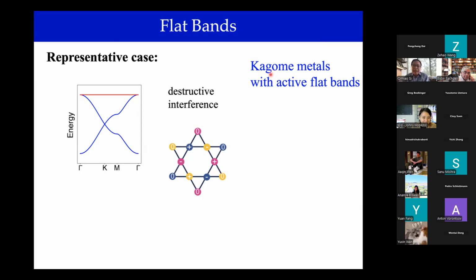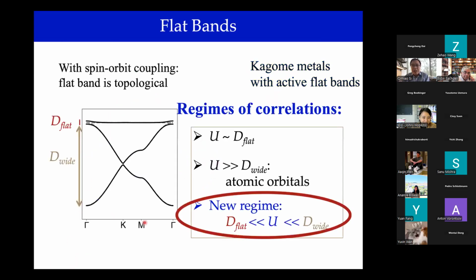is something like Kagome metal. If the chemical potential is sufficiently close to the flat bands, then the flat bands become active. The flat bands here are formed not by atomic physics per se, but by the destructive interference enabled by, say, the geometrical frustration of the lattice. And this leads to actual regimes of interaction physics by just looking at the hierarchy of the bandwidth. If the flat bandwidth is much smaller than the wide bandwidth in the kinetic part, then I have at least 3 regimes of interactions as opposed to 2. The Coulomb interaction could be comparable to the flat bandwidth. And if the chemical potential is sitting in the middle of it, that will lead to all sorts of electronic order due to the enhanced density of states.